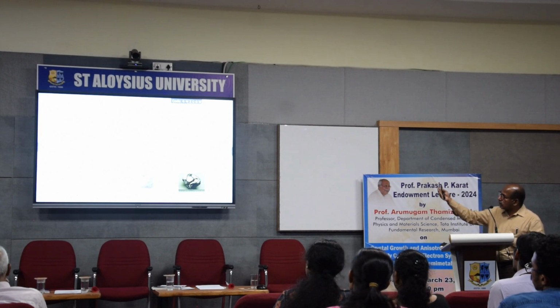So for a cubic, sometimes you will end up with this kind of triangular pattern. That is because of how the growth units are attached to the crystal. Initially a single nucleation happens and a large crystal grows, and when the next nucleation happens, a step arises. Inside the step you have some kinks, and the kinks are the most preferred places for the growth units to get attached. If you see the right-hand side figure, K is the kink site, S is a step, and F is the flat.